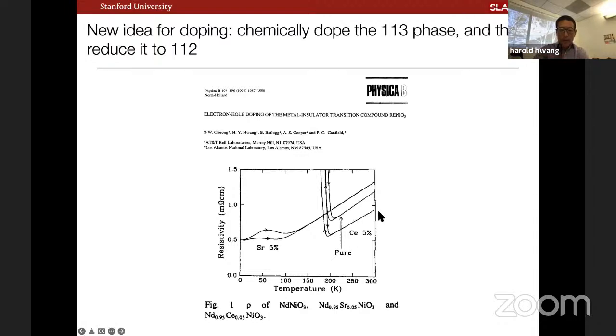It has a very dramatic first order metal-insulator transition from a high temperature paramagnetic metallic phase to a low temperature ordered antiferromagnetic insulator. And we had fooled around a little bit with doping this system. It's ironic that some 25 odd years later, we came back to this issue of trying to use substitutional doping. So the idea was as follows: let's chemically dope the perovskite phase first, and then reduce it hopefully to the infinite layer phase. And that might be the way we can approach systematic carrier doping.